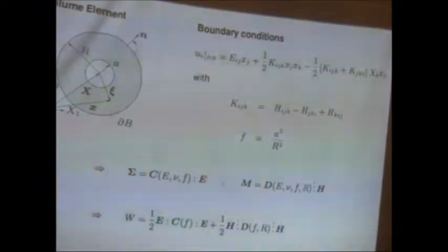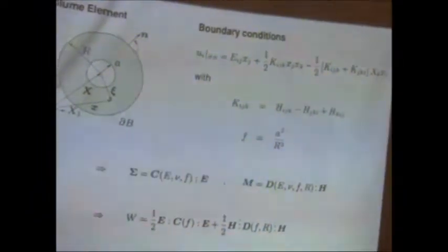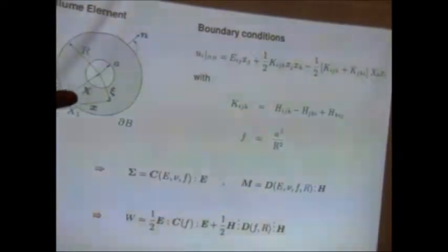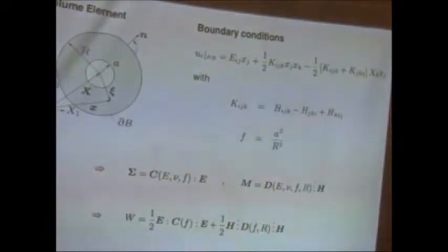Actually we are going here for the most simple case we can imagine. It's a plane problem even, not even 3-dimensional. But the nice thing here is that eventually we get an analytical solution which helps us to interpret the results at this stage more transparently. I'm showing this because this is one way to get the strain energy density for strain gradient elasticity and relate the additional constitutive relations directly to the microstructure.